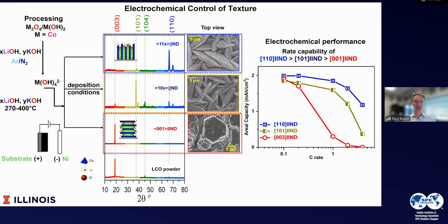And you can just see over here the impact on the rate performance. When it's vertically oriented, it has very good rate performance. When it's horizontally oriented, it has very poor rate performance. And that's because here the fast transport directions are aligned perpendicular to the current collector, and here they're parallel.